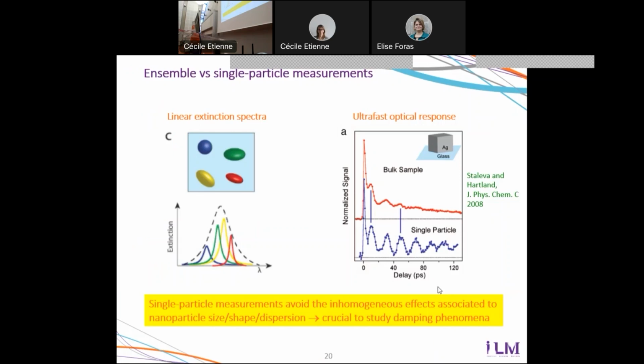In some cases, it's not such a problem, but in other cases, it can be a big problem, especially when one is interested in damping phenomena, for instance, vibrational damping. You can see here that when you perform experiments on assemblies and on a single particle, you will have here a very strongly damped signal, and here a much less damped signal.